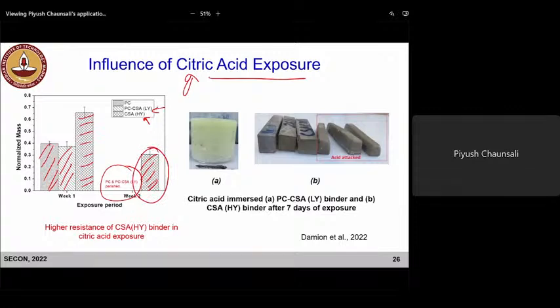So there's at least higher resistance of CSAB cement, in this case high ye'elimite cement, in citric acid exposure. You can see the difference, right? So this is PC dominated, like Portland cement when it is 100% or when 10% is replaced with PC-CSA admixture. So that's what happened. And here you see the high ye'elimite system. So current work is looking at different types of acids and different concentrations, so that we have a better idea what kind of formulation will have higher or lower resistance. We are trying to understand this better.